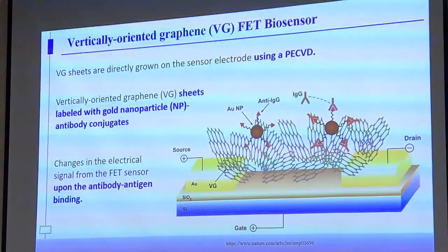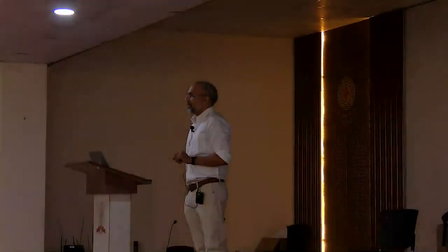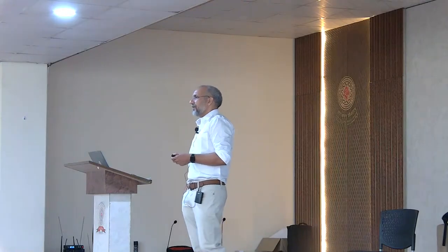When you have graphene or carbon nanotubes, if they are pristine, it's very hard to do any type of functionalization. But if they are defective themselves, then it's very straightforward to do functionalization. Especially for graphene, if you grow graphene using the chemical exfoliation method, like the Hummers method, for example, first you produce graphene oxide, right? And you reduce the graphene oxide, then you have the reduced graphene. If that's not perfectly reduced, you already have those functional groups where you can play the chemistry. It will be very straightforward there.